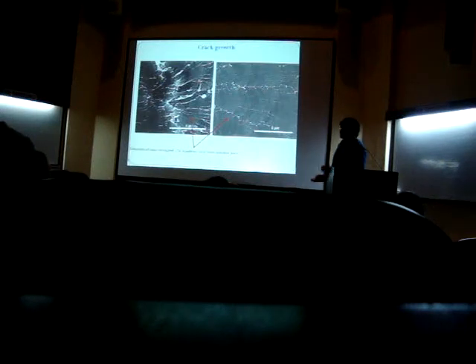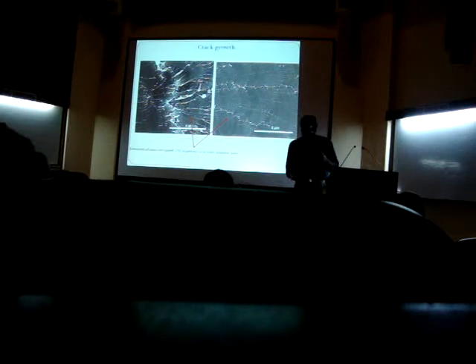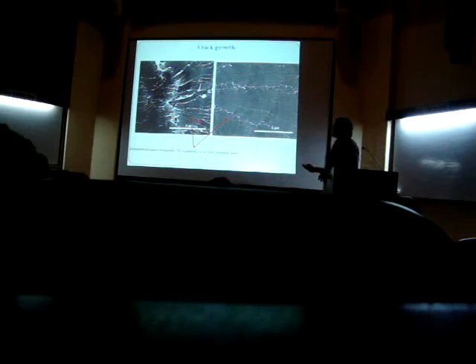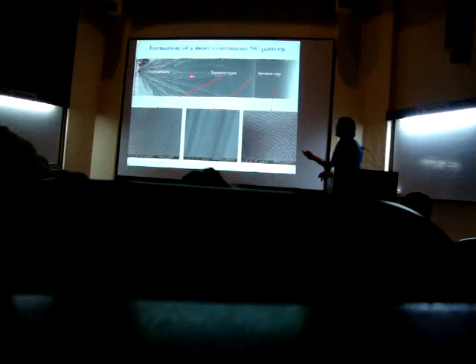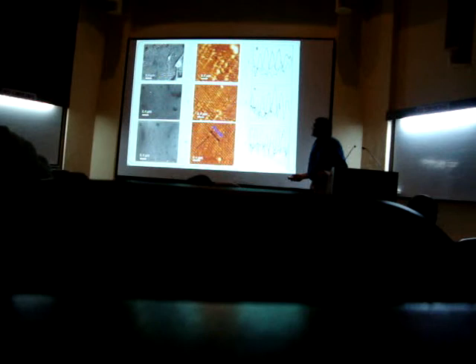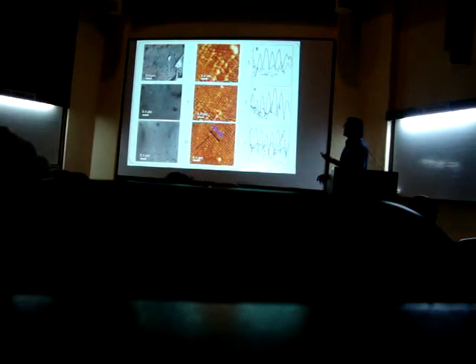And now, moving on from crack initiation, we look at aspects of crack growth, and you see these spider web-like patterns which extend from the notch tip. So this is your notch edge, and the cavity at the notch edge, and they form these patterns. The patterns become more and more regular as we move away from the crack initiation point to the specimen edge. You see that they become nanotrenches. And we want to see what the characteristics of these nanotrenches are.